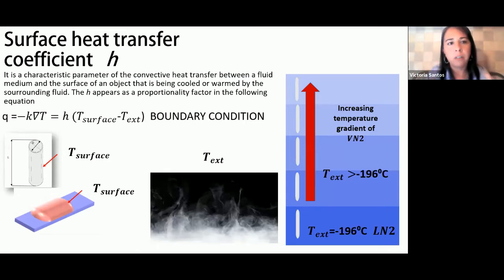And an important aspect of the equations is that we need the boundary equation. The boundary equation involves the use of the surface heat transfer coefficient, which is a very important engineer parameter. It is a characteristic parameter of the convective heat transfer between the fluid medium and the surface of the object that is being cooled or warmed by this fluid, which surrounds the entire object. The H appears as a proportionality factor in the equation. Here you can see H times the temperature of the surface minus the external temperature. The temperature of the surface is the surface of the object, the OPS or the cryotop, and the external temperature would be the temperature of the nitrogen vapors.